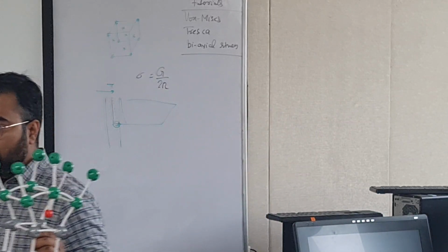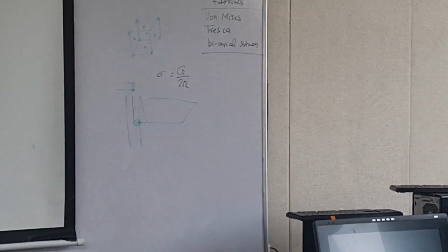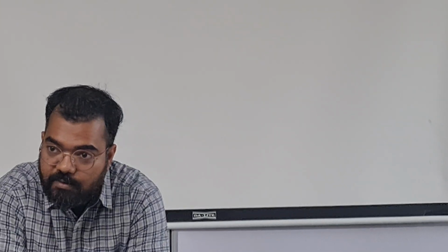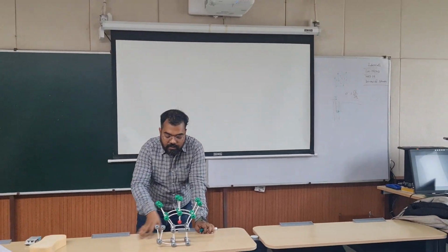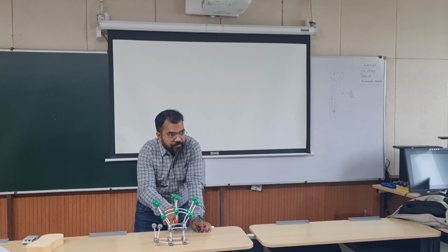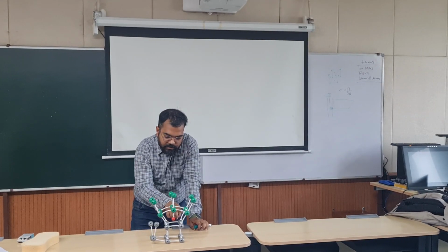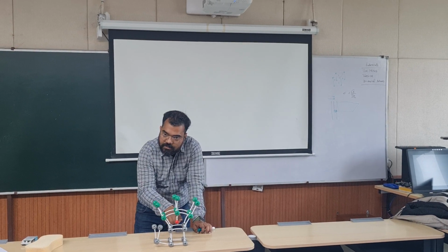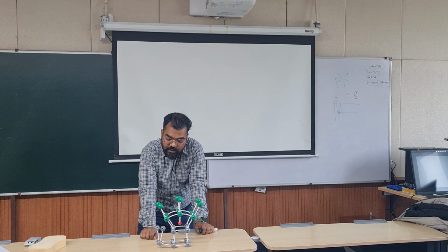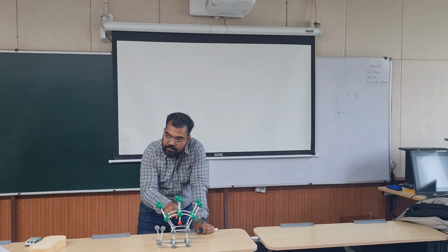So that's what I wanted you to know, that it will not move on the planes which you draw, okay? So this is a model of a dislocation which we were discussing yesterday, no? So you see, this is the extra half plane. This one. Okay, I don't have too many balls to make the whole crystal. And below this is missing. Yes. Because of that, you see the distortion I was talking about. This is the amount of distortion the lattice will have. Okay, so there will be a tensile stress field and there will be a compressive stress field.